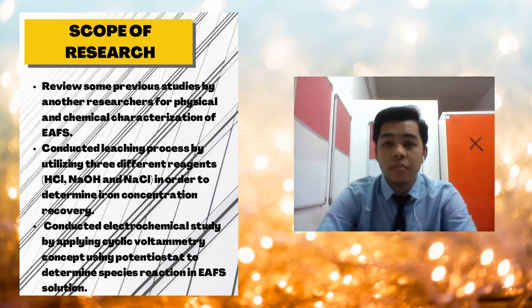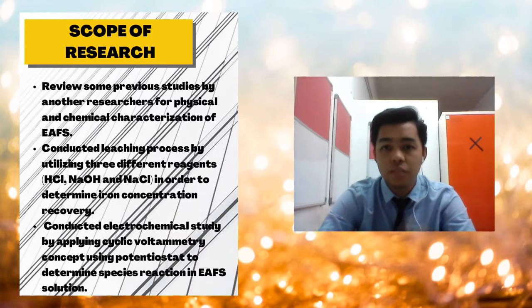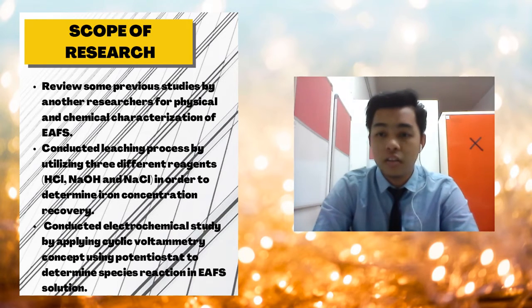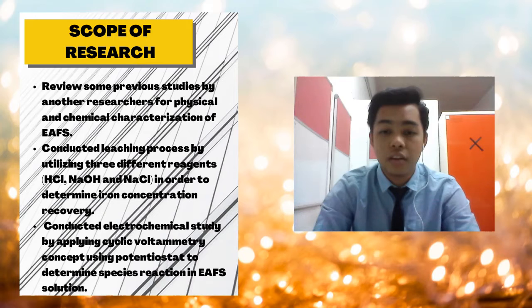For physical and chemical characterization, the study focused on reviewing previous studies by other researchers. Meanwhile, for electrochemical characterization, two experiments were conducted. Firstly, by conducting a leaching process utilizing three different reagents: hydrochloric acid, sodium hydroxide, and sodium chloride, in order to determine iron concentration recovery. The second experiment was conducting an electrochemical study by applying the cyclic voltammetry concept using a potentiostat to determine species reaction in EAFS solution.